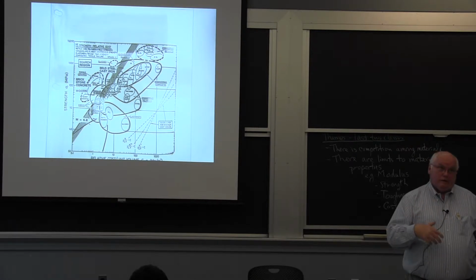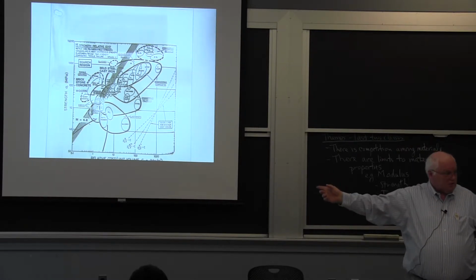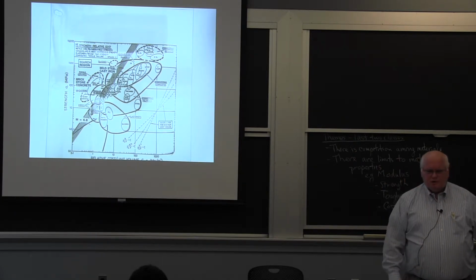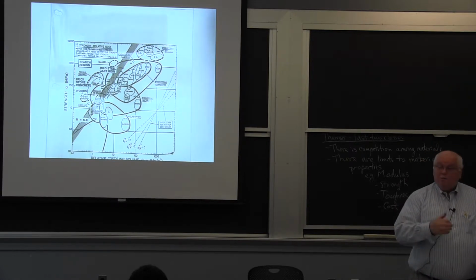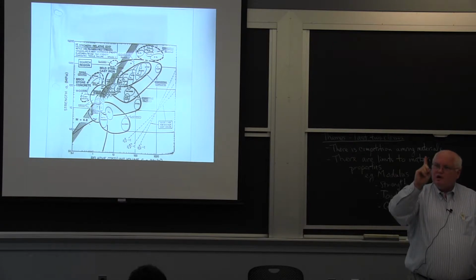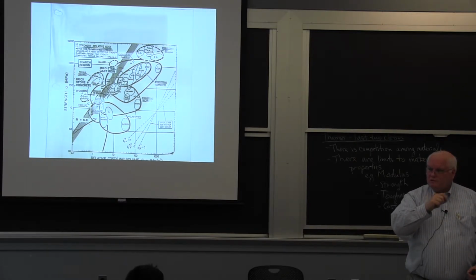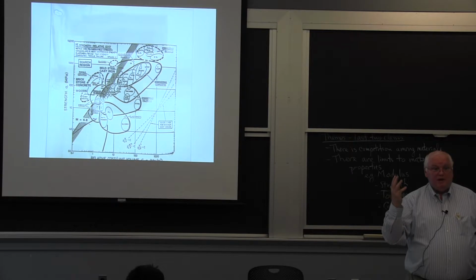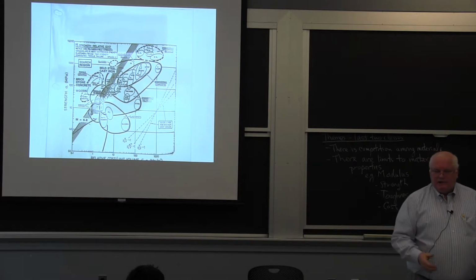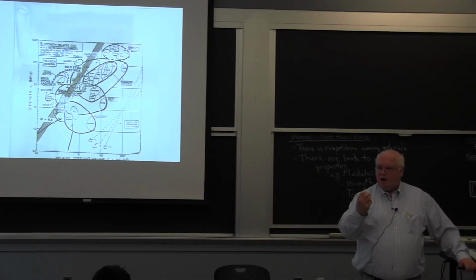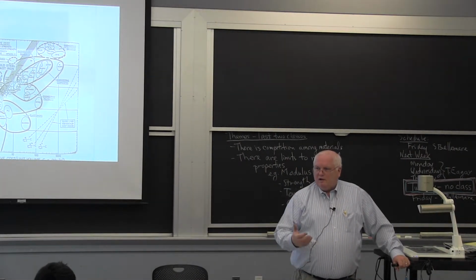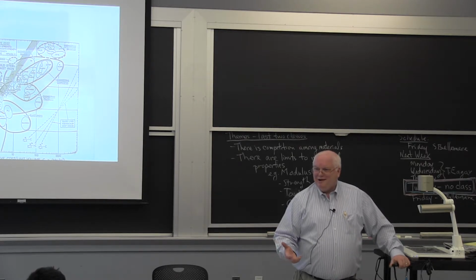The calculation was done back in the 1920s when they first came up with these potentials. Physicists calculated and said, "Oh, material should be 3 million psi." People said, "You're wrong. We never measured any material with 3 million psi." By the 1950s, they had made iron whiskers with a screw dislocation right up the center, and when you pull that in tension, there's no force on the screw dislocation, so it's like a single crystal, even though it's got a screw dislocation, but in the wrong direction to the stress. And they got 2.8 million psi on those iron whiskers. You take sapphire fibers, over 2 million psi. And so NASA in the 1980s was having people here at MIT and other places grow sapphire fibers. They were going to incorporate that into structure. Well, that's fine. But sapphire fibers were worth more than copper.